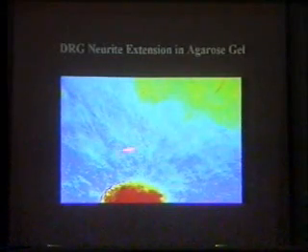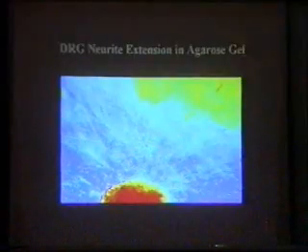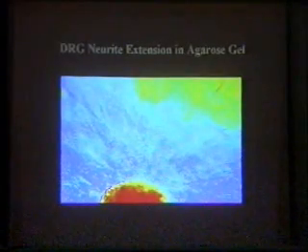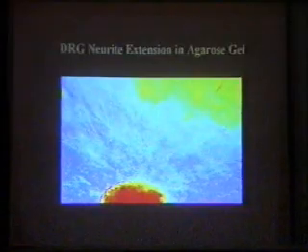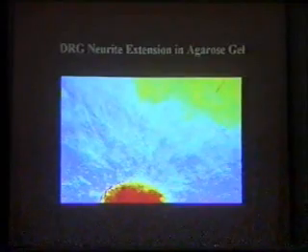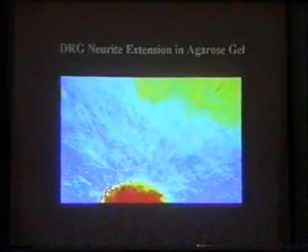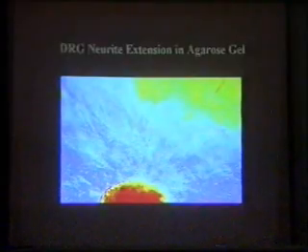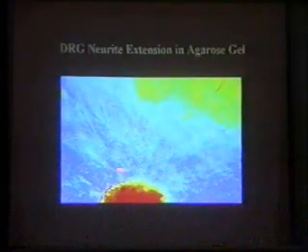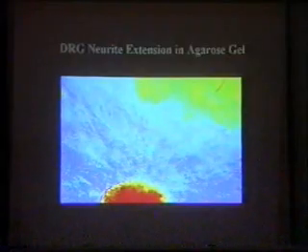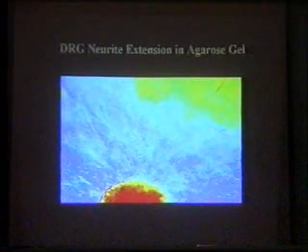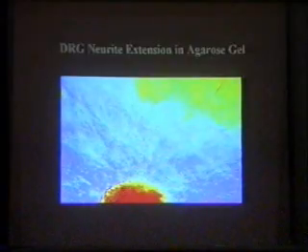During my graduate work, we identified a subfraction of agarose, which is derived from seaweed. This is a hydroxyethylated version of agarose. On the backbone of agarose, you can substitute hydroxyethyl chains, and depending on the length of those chains, you can control the gelling temperature of agarose. We use a kind of agarose that gels at about 17 degrees centigrade. If you mix in the solution of agarose with no modifications and put in a dorsal root ganglion, which is a collection of neurons, they grow embedded within the gel and send out beautiful neuronal processes.